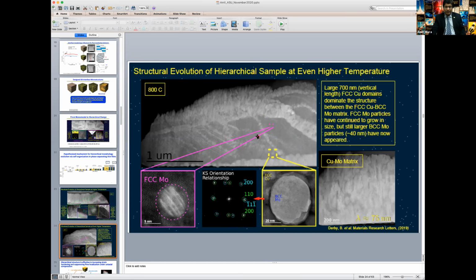Yeah, right. But a lot of these things have not been studied because they were not observed in these vapor deposited films. Certainly, the kinetics that comes in with the deposition of a layer alters a lot of things because things are highly out of equilibrium. Whereas when you take a block and just anneal it with some moly mixed, it will be closer to equilibrium. It will have time to relax and diffuse. So that's an interesting comparison.